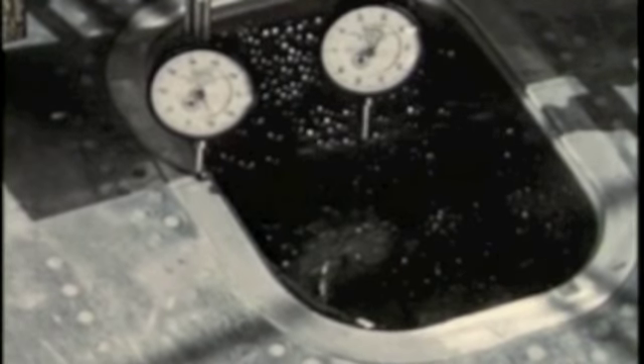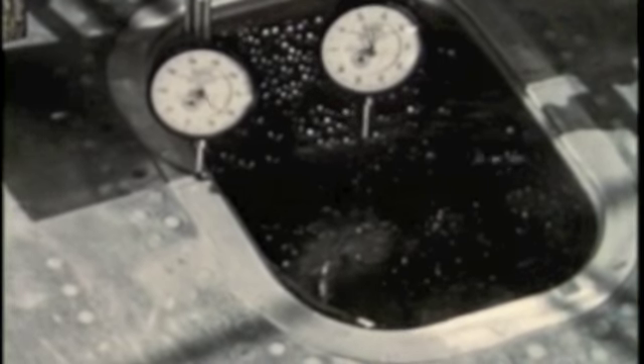Extensive fatigue testing of the forged window frames designed for the 880 has been conducted with satisfactory results. Other pressure tests conducted on the single inner window bore out that it can withstand double the normal cabin pressure. This proves that the single inner window would hold even if the double outer windows were lost.